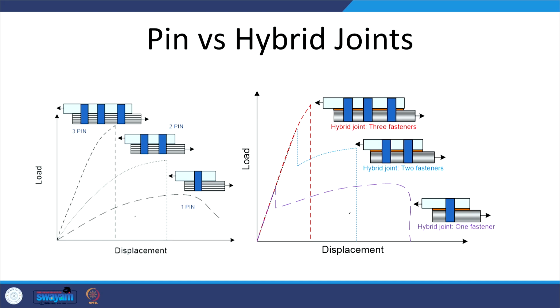Okay. In hybrid adhesive joining, if in the sheets you use just one fastener, it means only this shear area is available. So, our load carrying capacity and load displacement curve will be like this when just one pin is used. Our load carrying capacity increases significantly, but the elongation is reduced when you use 2 pins. When 3 pins are used, the load carrying capacity is enhanced, but the displacement is reduced further. But when we club it with the adhesive bonding, we get something like this.